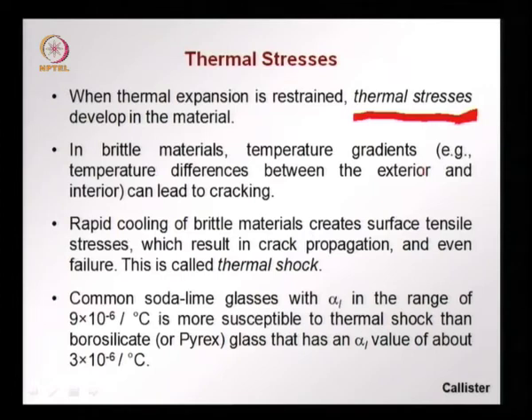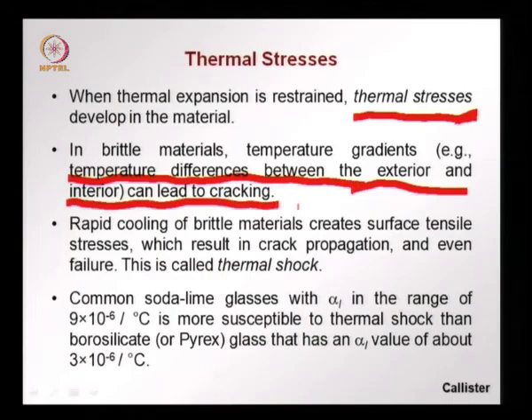lower than what is inside, you will have contraction on the outside, cracks developing from the outside to the interior. This happens for example in a massive concrete element. Just after setting starts, hydration has just begun, the temperature inside goes up because of the exothermic reaction, whereas the outside in contact with the ambient temperature can undergo cooling. This leads to contraction and you have now cracks developing from the outside to the interior, and these cracks could stay in the structure and harm the structure later. So, temperature differences between the exterior and interior can lead to cracking in brittle materials.